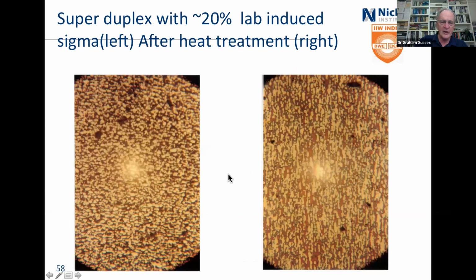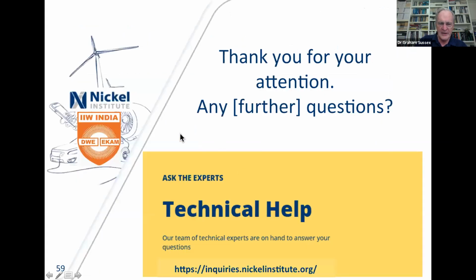If you start looking at the things in detail, this had 20% lab-induced sigma phase, and sorry for the lousy flare in the middle. You can see the black color here, and then it was heat treated, and you're back to having the ferrite and austenite, so very, very low levels of sigma phase. And that's it. I just about finished on time.